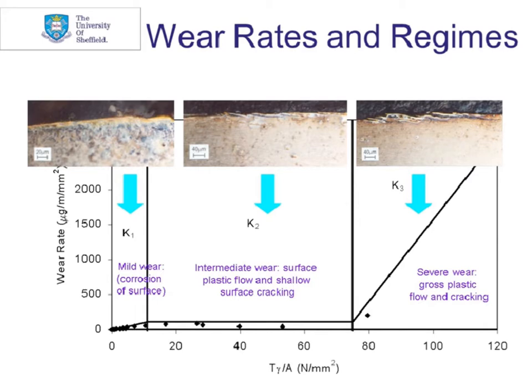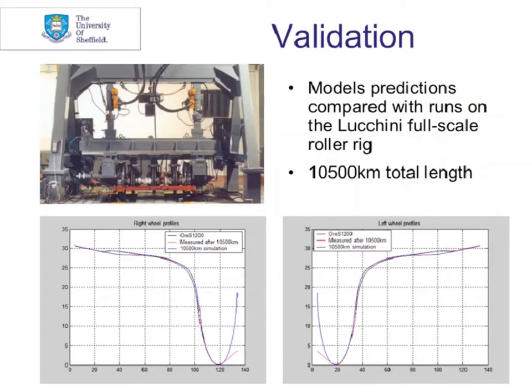Obviously, these tests were carried out in dry conditions. In order to validate, we were lucky enough to have access to some data from the Lucchini full-scale roller rig, quite an impressive test rig, as you can see, that allows you to mount a whole axle within a rig and load it and undergo an actual train mission. Again, though, this is in a lab, so it's dry conditions. Actually, that was convenient in this case because we had a dry prediction and dry validation case. We could do a really good comparison, and you can see here that the prediction matches very well what was measured in the rig.